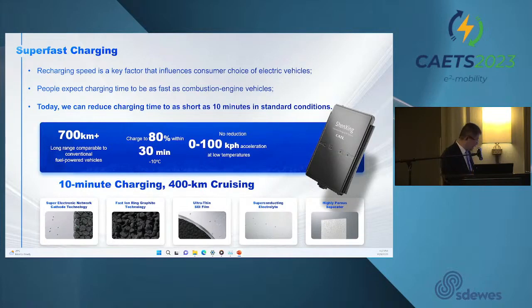For this technology, here I show some examples. New technologies of super electronic network and nano-structured lithium-iron phosphate cathode materials have been applied to improve lithium-ion diffusion. For the anode, we have developed a fast ion ring on the material surface to increase the ion insertion channels and improve ionic conductivity. We also deployed a multi-gradient layered electrode to balance fast charging and high energy density during cell manufacturing. For the battery cell guys, you should know fast charging and energy density are usually not easy to increase together. So we do some balancing.